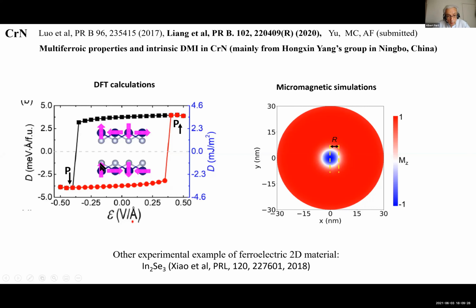This one corresponds to a clockwise rotation and counterclockwise in this direction. So there is a possibility of having in this sort of system, due to the breaking of inversion symmetry, Dzyaloshinskii-Moriya interaction and skyrmions, and the simulation confirms that the size of this DMI allows one to produce a skyrmion. Of course, the advantage is that depending on the polarization, it will be possible in this system to produce a skyrmion of different chirality.